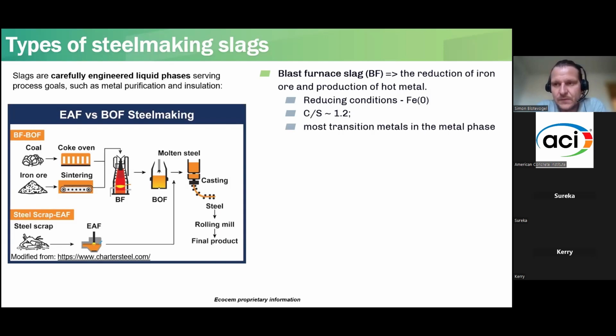In Europe, it's about 70-30% of the production via the blast furnace, basic oxygen furnace route, and 30% via the steel scrap route, whereas in the US, it's the other way around. All the steps where you melt the metal will produce a slag.